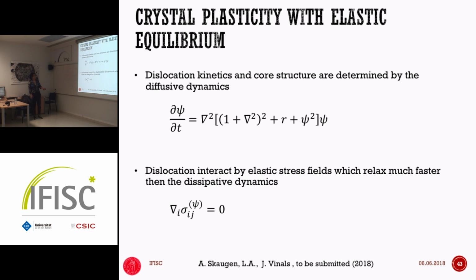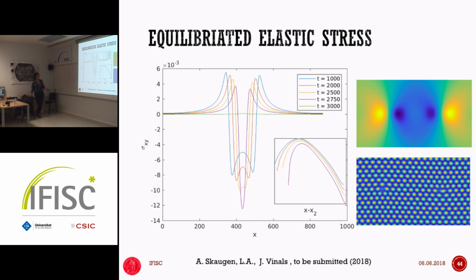However, if we now constrain this mechanical stress, this elastic stress, to be at equilibrium at all times, and there's a little bit of technicalities involved numerically in how you constrain this, because there's a huge separation of timescale. So we want to evolve the psi field on this diffusive time scale with the constraint that at each time the stress field, determined by this psi field, is at mechanical equilibrium. But we have a scheme by which we can do this, and what we obtain is that when we do the same setup, the same initial condition, the power law of 1 over r predicted by the linear elasticity is very nicely preserved at all times. The dynamics is also very different and happens much faster.